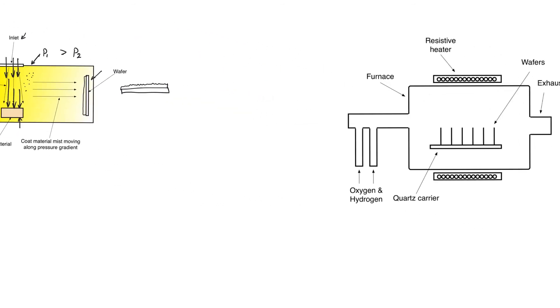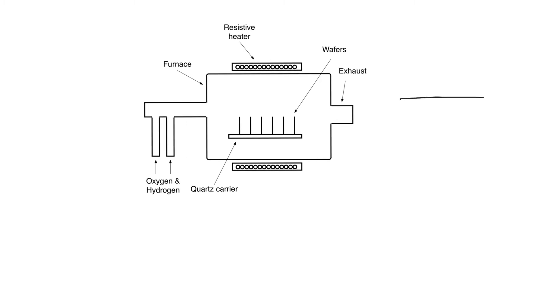There's also one more thing about forming silicon dioxide. We have to distinguish between when we have the wafer and we have access to the surface of the wafer, such as when we start the first step of photolithography. In this case, if we want to build silicon dioxide on top of the wafer, we use oxidation, which means that we just expose the top of the wafer to heat and an oxygen rich environment, allowing the silicon on the top to react and form silicon dioxide. If we have already formed features on top of the wafer, like wires or polysilicon gates, and if we have already built a layer of silicon dioxide using oxidation, we can no longer add silicon dioxide by oxidizing the substrate because we no longer have access to the substrate. Any further addition of silicon dioxide is usually done using CVD.